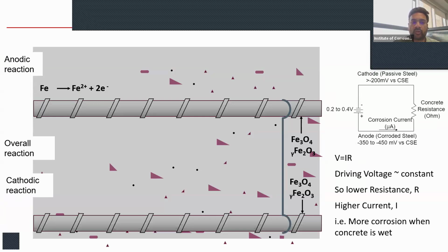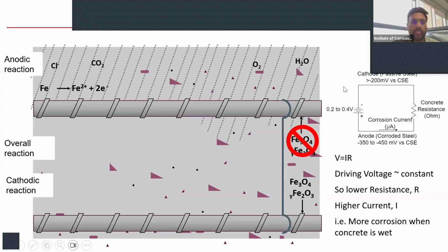As soon as the hydration of cement starts, there's a formation of a passive layer on the steel, which is gamma Fe2O3. But since concrete is porous in nature, it leads to ingress of chlorides and carbon dioxide, which causes this passive film to break.